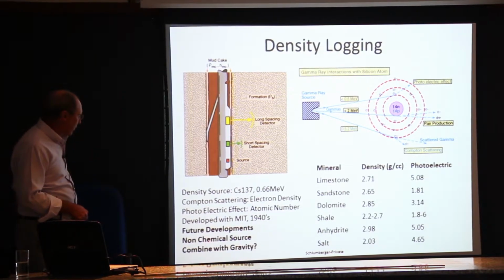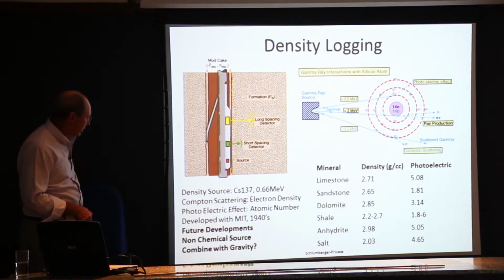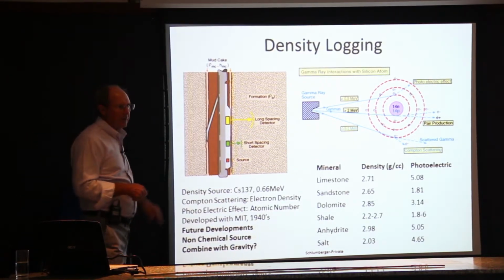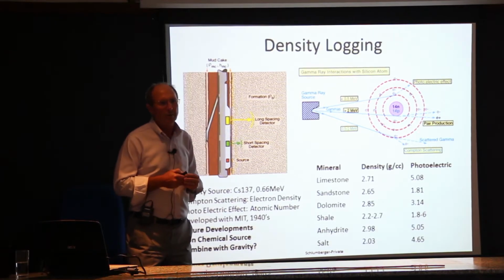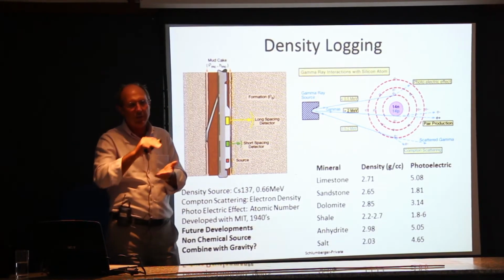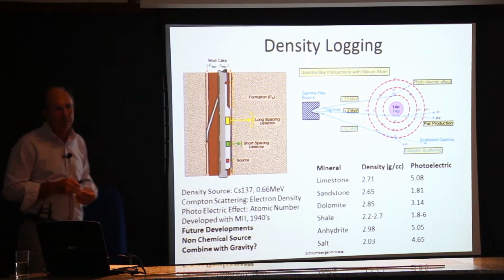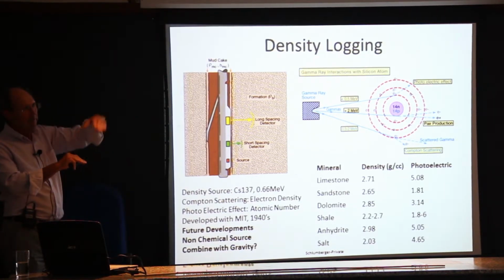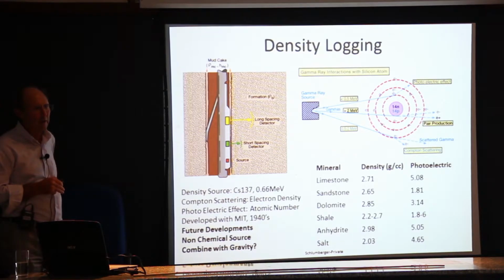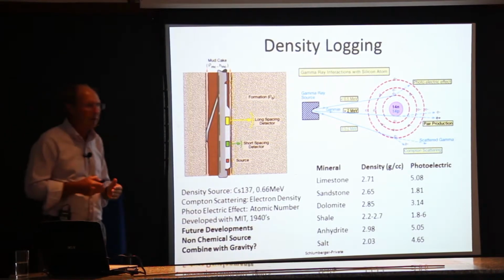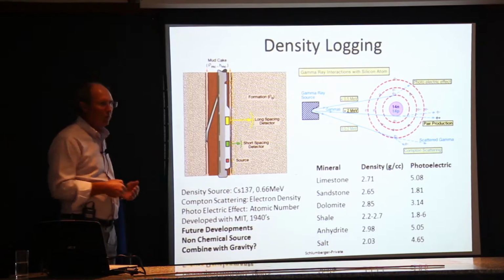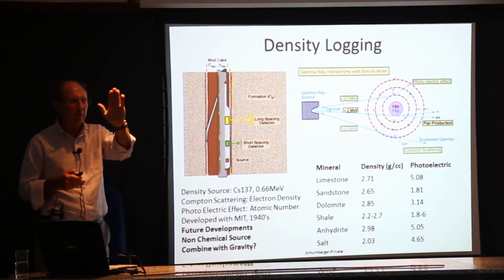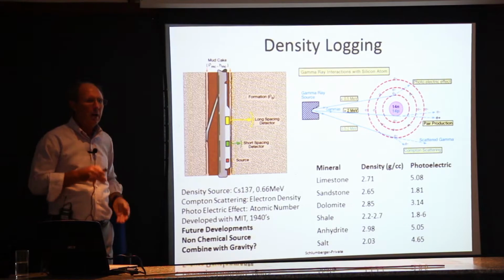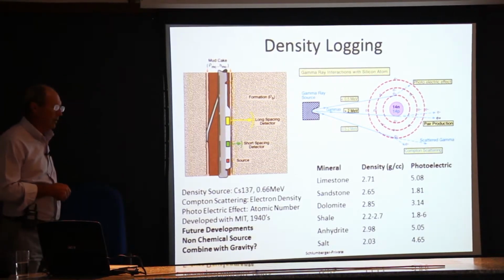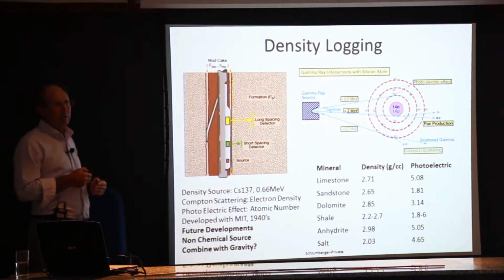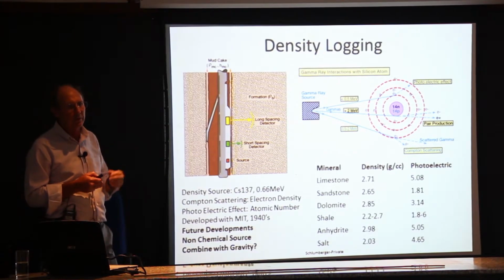Now, one of the interesting things we see in the pre-salt is what we call karsted formations, which are essentially big caves downhole, with very high porosity, and they can be a few feet thick, sometimes 10, maybe 20 feet thick. And when you see these karsted formations, often the wireline tools won't work that well because you don't have good contact with the borehole wall in these highly karsted formations. So we have a difficult time evaluating what the true porosity is in these karsted intervals.